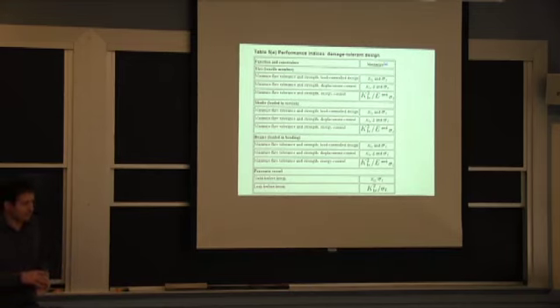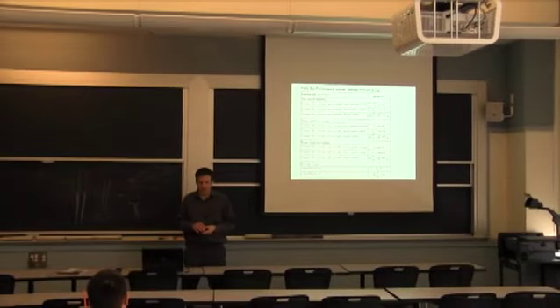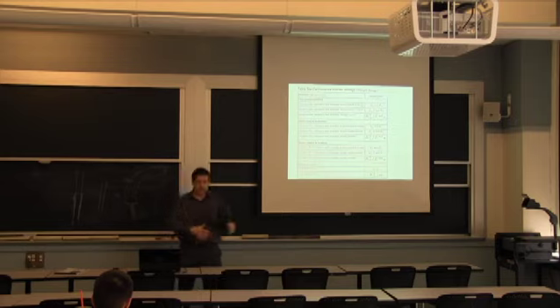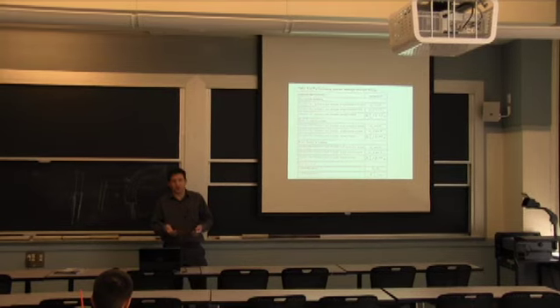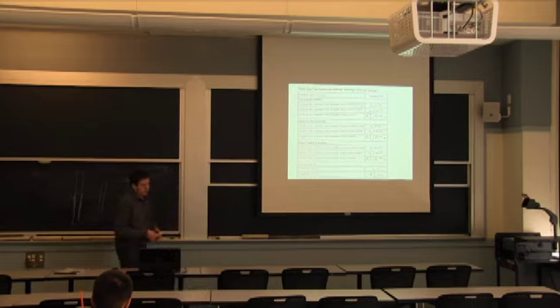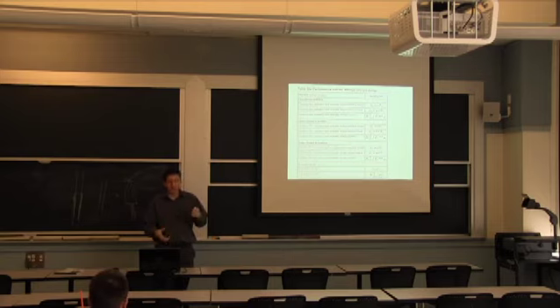So if I have a design for a bicycle that I'm trying to compare aluminum and steel, it will be a very different shape. And I think you already know that from the beginning, but the way you optimize each shape is based on, in one case, more of a local buckling effect, but also the joints. Aluminum has lower strength joints, but if you weld bigger tubes together, your moment of inertia between them is more favorable, and you don't have any brittle behavior that's expected if it's welded correctly. So there are advantages to both materials. It's just, when we're talking about a significant change, changing density by, say, 2.5, a lot of other things should be done the same way to be able to optimize both designs.